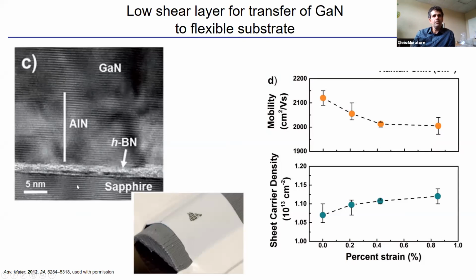And to grow it, usually on a sapphire substrate, you put an aluminum nitride layer between the sapphire and the GaN. And this does some things. It's a good buffer between the lattice parameter of the GaN and the sapphire, and you can accommodate some stress in this layer. And what we've done here is introduced boron nitride between this stack that's for the GaN and the substrate.